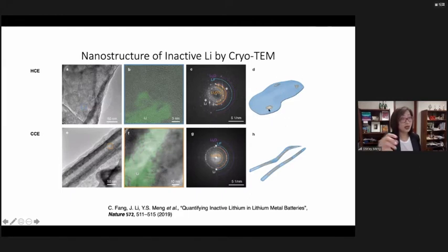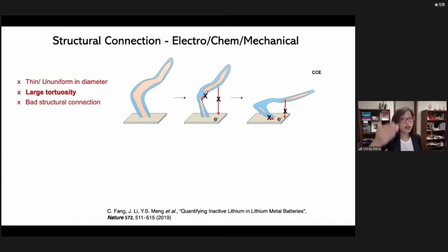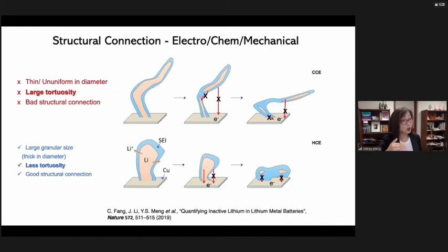You can see that if you have large granular particles, very little lithium gets stuck in the SEI. But if you have those tortuous, very elongated, high aspect ratio lithium metal, it's very highly likely you will run into the situation where the lithium metal loses its structural connection with the current collector. In electrochemistry, you need both the ion pathway and the electron pathway. So if the blue part, the SEI, is too insulating, you cannot access a very good electrochemical system. That's the reason in our Nature paper we hypothesize that the SEI is not the major culprit for low efficiency lithium metal batteries, but the microstructure control is.